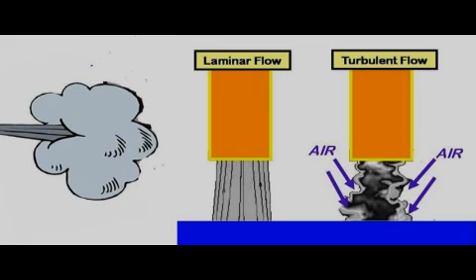In the presence of drafts, higher flow rates can be used up to a limit. It is important to avoid creating excess turbulent flow that will pull air into the shielding gas stream. In 1893, Osborne Reynolds defined the flow rates that establish smooth laminar flow, which is needed for quality shielding, versus turbulent flow that causes moisture-laden air to be mixed with the shielding gas stream.